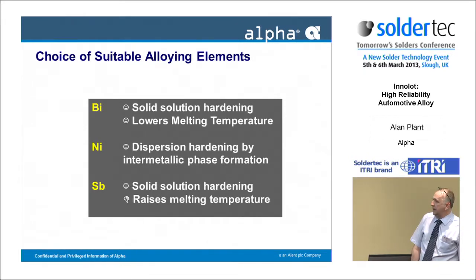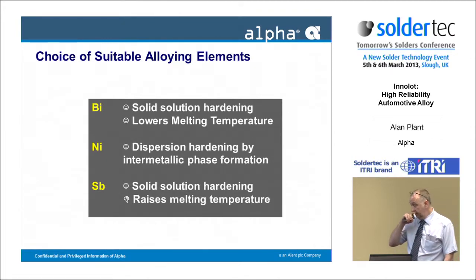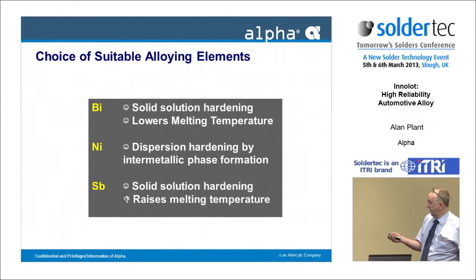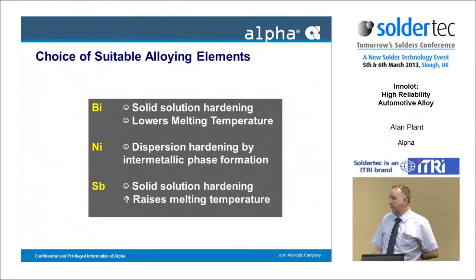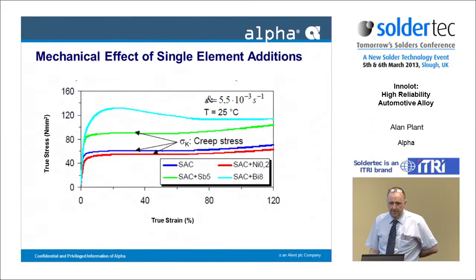common elements that have been used in solder alloys over the years, either as binary or even ternary systems. So bismuth, it gives us a solid solution hardening. We know it lowers melting temperature, two of the things we wanted to do. The nickel, we knew it could give us dispersion hardening. And then the antimony, again, solid solution hardening, but the thing it did here that we didn't want is actually raise the melting temperature.